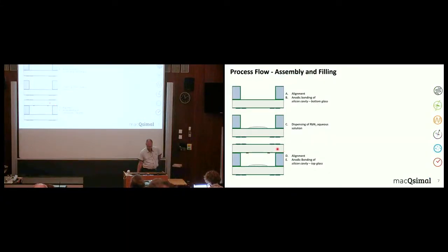we align the top wafer on this preform, and we do another anodic bonding, which then takes place first under high vacuum, and then we fill back the chamber with argon to have the argon atmosphere inside. And now you see here in this configuration, gold discs, they are now sitting inside the chamber, and yeah, so this is the fabrication process of the atomic vapor cells on a wafer scale.